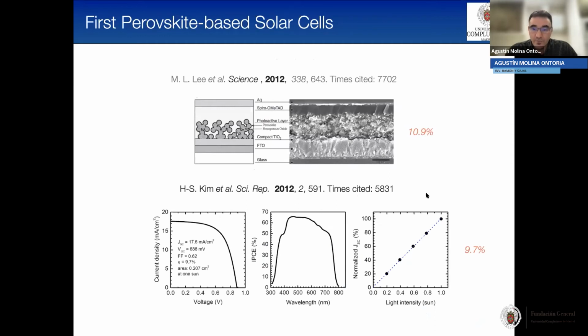Well, the next breakthrough in this field was to remove the liquid electrolyte and substitute it with a solid material, solid electrolyte or solid hole transporting layer. In this case, this was spiro-OMeTAD. So just by doing that, the efficiencies jumped from 4 to 11%, or close to 10%. And these papers were published more or less at the same time by two different groups. This paper by the group of Henry Snaith, and this by the group of Professor Michael Grätzel.